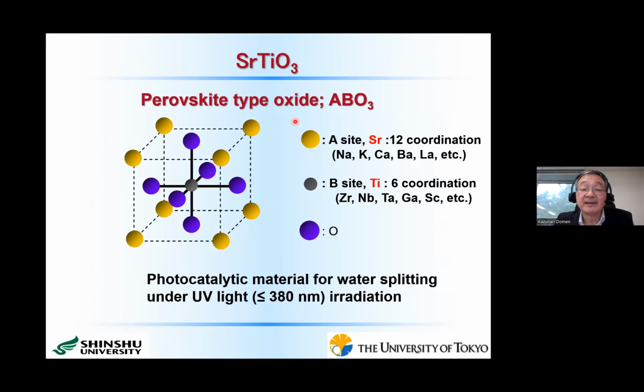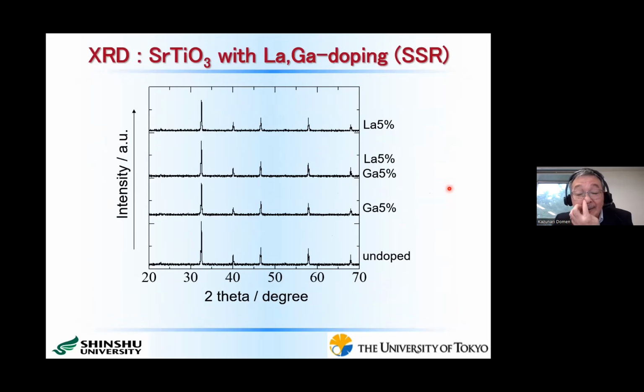The structure of this material is the very well-known perovskite type structure, and the A site cation is strontium 2+, and the B site cation is titanium 4+. But these A and B site cations are very easily replaced by various kinds of different cations. Here I show our experimental result, the X-ray patterns of several doped strontium titanates prepared by solid state reaction, I mean calcination in air. This is undoped strontium titanate, and these are gallium 5%, lanthanum 5%, and gallium and lanthanum 5% doped samples.